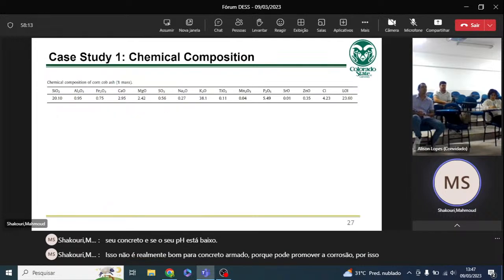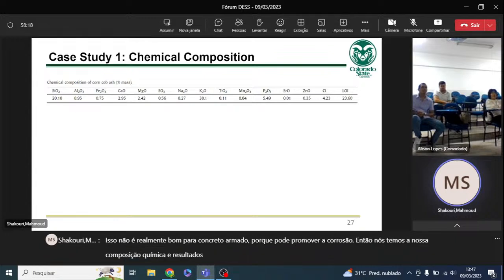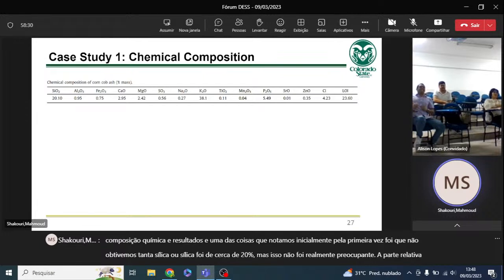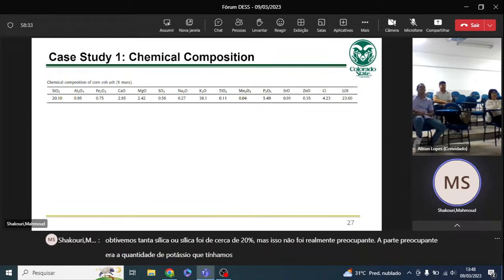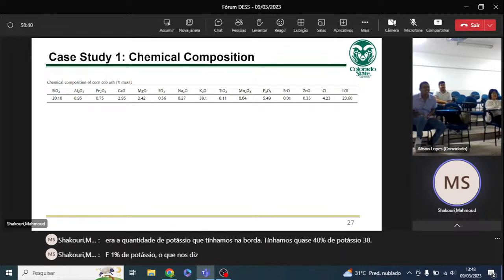So we got our chemical composition results, and one of the things that we first noticed initially was that we didn't get that much silica. Our silica was about 20%, but that was not really concerning. The concerning part was the amount of potassium that we had in the ash. We had almost 40% potassium, 38.1% potassium, which tells us that they probably used a lot of fertilizers to grow that corn, because potassium comes from fertilizer.